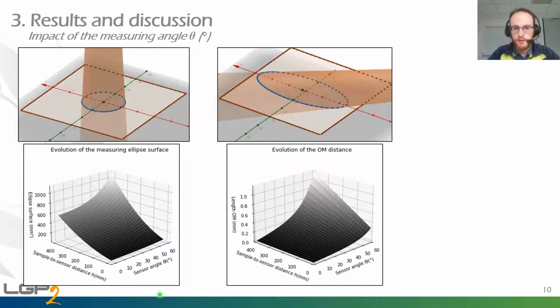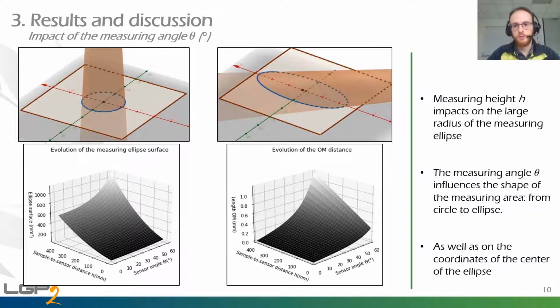We'll have the same behavior for the OM distance, which represents the distance between the paper sample center and the center of the measurement area. And when theta increases, the length OM increases, and there will be an impact also of height. So measuring height impacts the large radius of the measuring ellipse. Moreover, the measuring angle theta influences the shape of the measuring area from circle to ellipse, as well as the coordinate of the center of this ellipse.